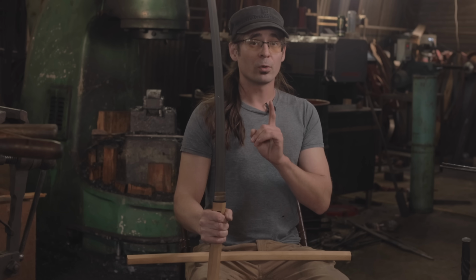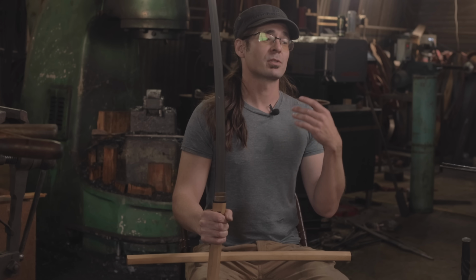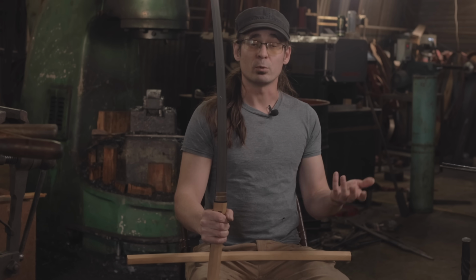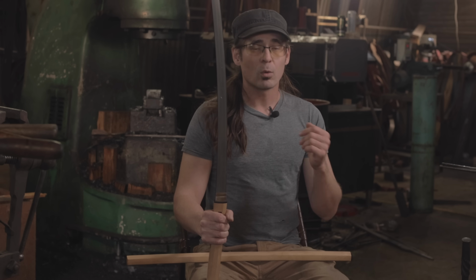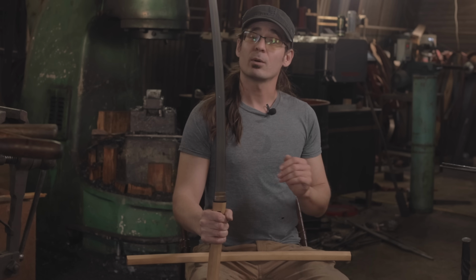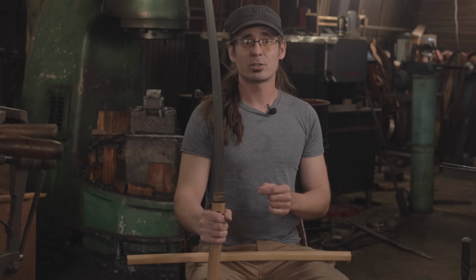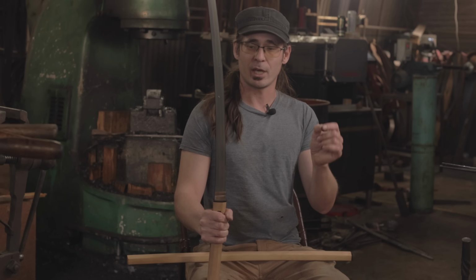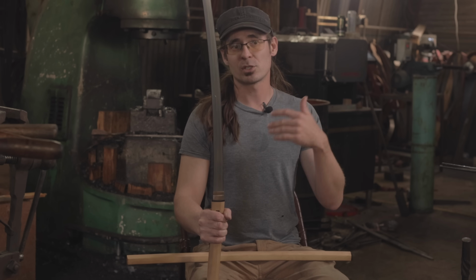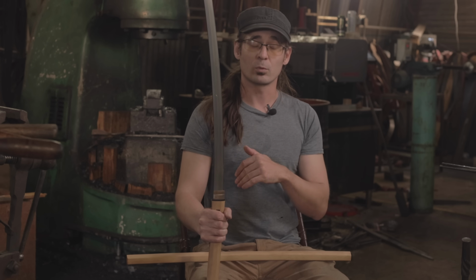However, the cool thing is, in our YouTube comments, people say, could you make a katana out of Wootz? I would not want to, because a straight up Wootz puck, if you differentially heat treat it, has too much tension between the edge and the spine and is more likely to crack than a non-Wootz puck.